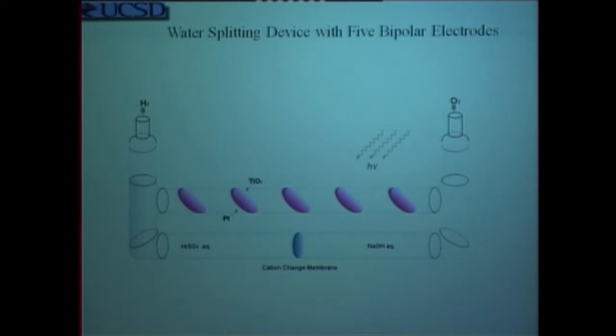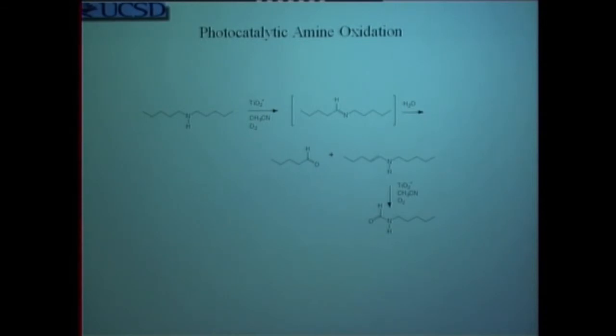Now, I mentioned to you that this works not just for water splitting, generating hydrogen, but it also works as a new means of controlling chemical reactivity. Virtually any molecule that has either a heteroatom or any conjugated double bonds will have an oxidation potential less than 2 volts, and as a result, it will be able to be reduced or oxidized in the transformation. So here's an amine.